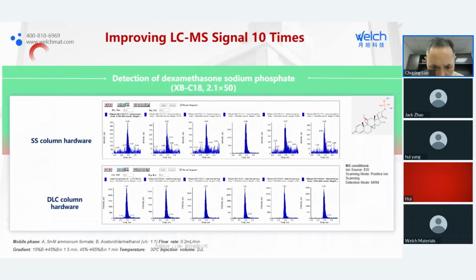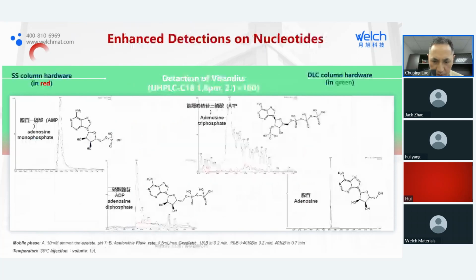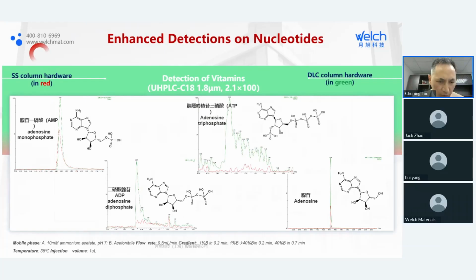Here's the data for the nucleotides. On the most left side, you see adenosine monophosphate. That's just one phosphate group. The green one represents the DLC column. The red one represents the stainless steel. It's clear that using the DLC system, the adsorption is significantly reduced. The same thing for the ones with two phosphate groups and three phosphate groups. And the last one is just adenosine itself. But even this, you'll see the better signal, the higher intensity using DLC hardware.